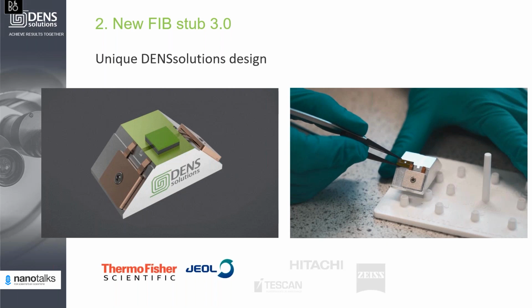So, how does the redeposition from the final milling affect the chip? Well, when we mill, we mill parallel, specifically for biasing experiments. We can mill away just the silicon nitride, but silicon nitride is just a support for us. It doesn't have any function of heating or biasing. So if we mill away the silicon nitride, it will not affect the functionality of the chip.